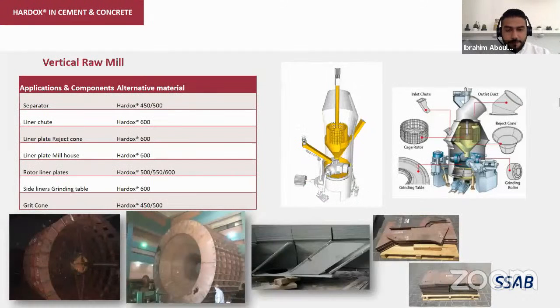Next slide, please. The most important part in a cement plant, the vertical raw mill. In the vertical raw mill, again, it grinds the raw material, or the raw mix, during the manufacturing of cement. And it is fed later on to the cement kiln, which transforms it to clinker, which will later be cement. So the raw mill undergoes severe wear on the grinding table and walls, as you can see in the gray liners at the bottom.